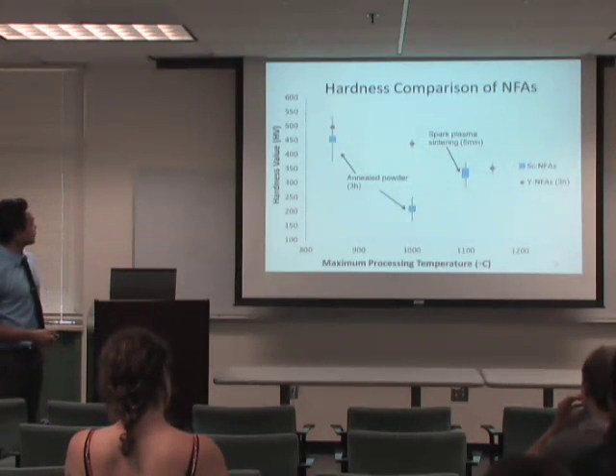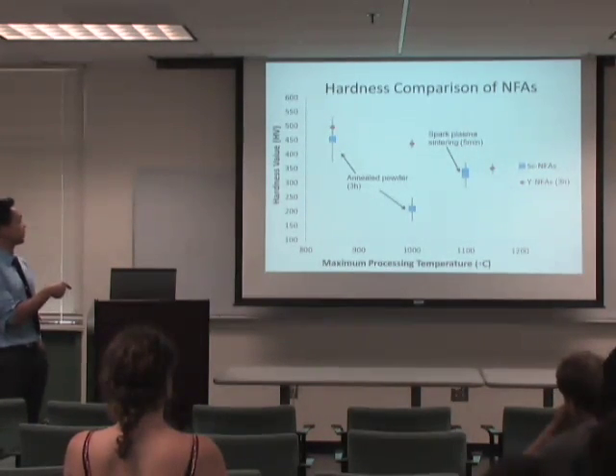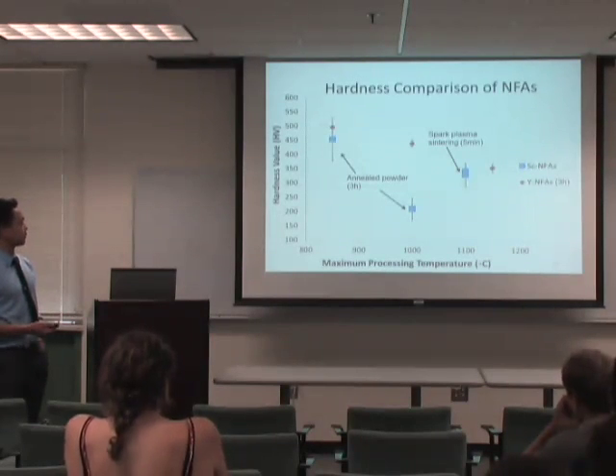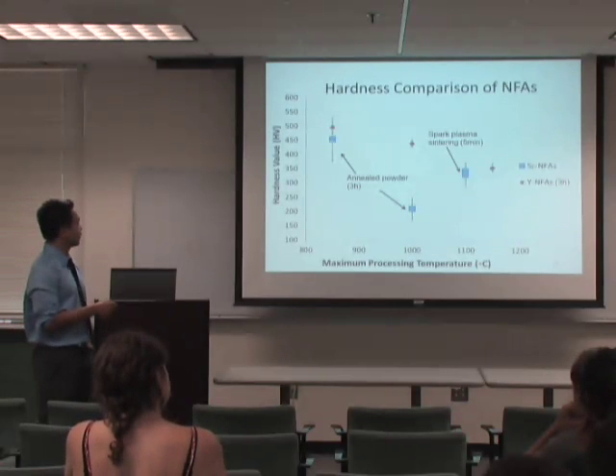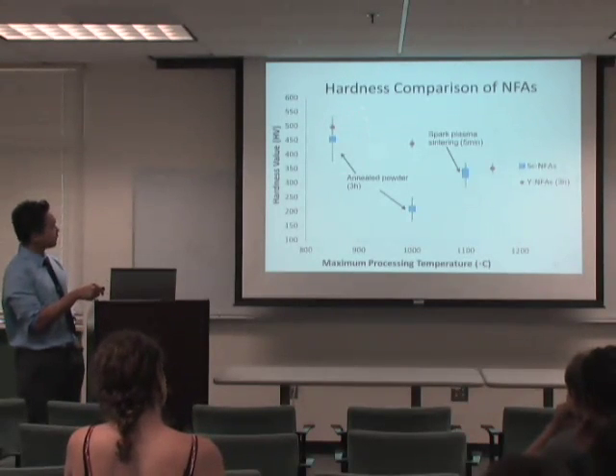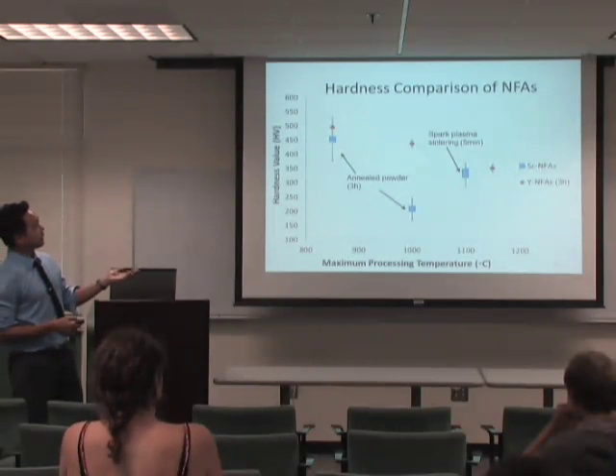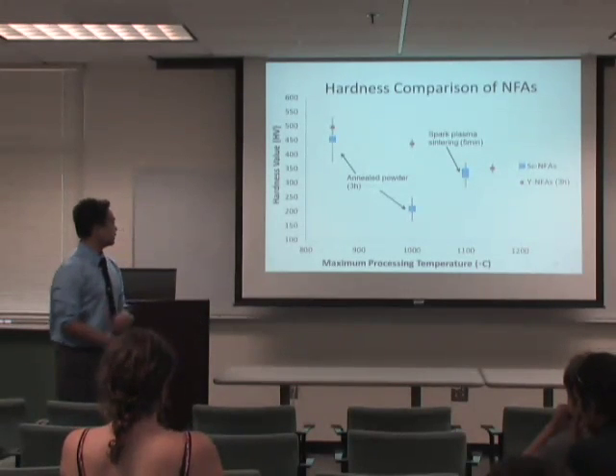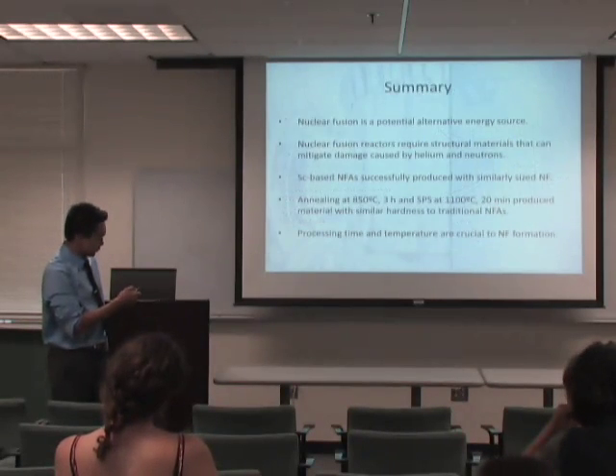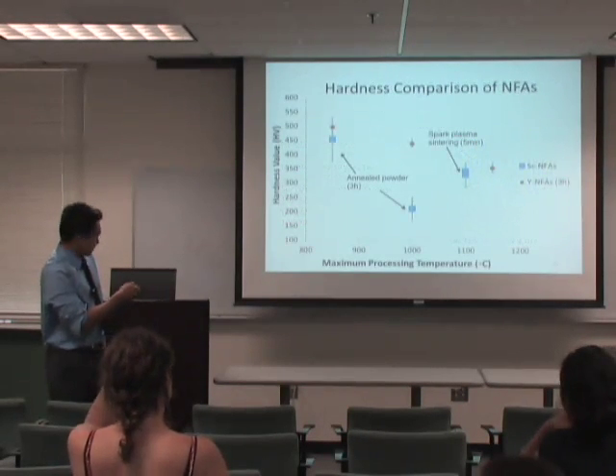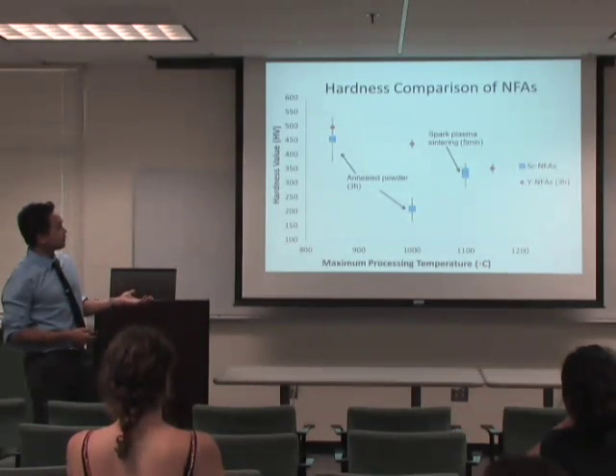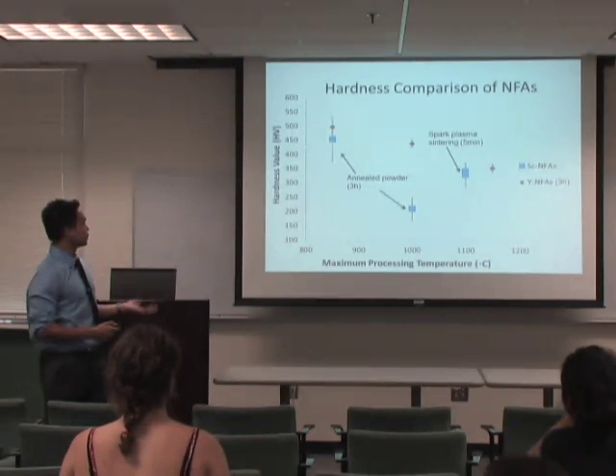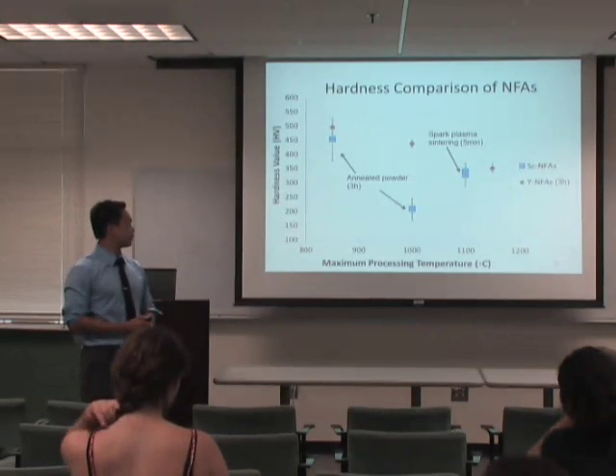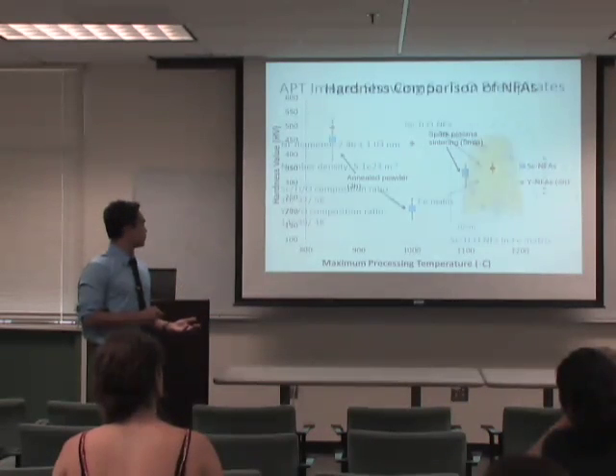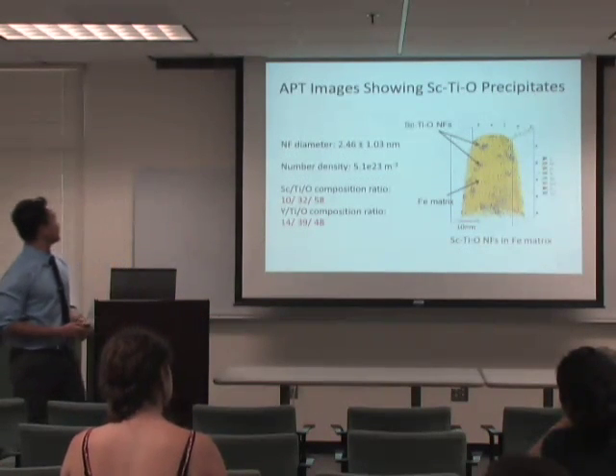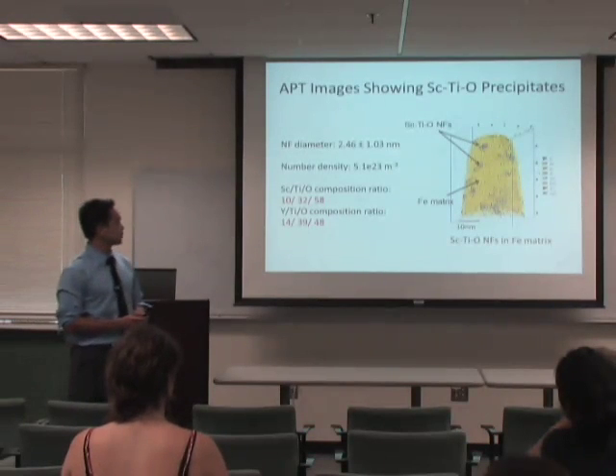And in this hardness chart, I've graphed the hardness value in terms of Vickers hardness versus the maximum processing temperature. Now, a couple of things to note here is that at 850 degrees Celsius and around 1100 degrees Celsius, my scandium NFA and my yttrium NFAs are fairly comparable. And another thing to notice here is at 1000 degrees Celsius, my scandium NFAs actually have a much lower hardness than my yttrium NFAs. My group came up with a couple of hypotheses about that, which I would be glad to explain in the question session. And here on your right is an image from Atom Probe.